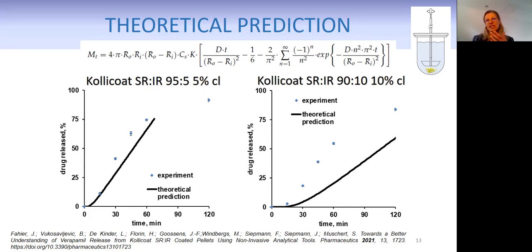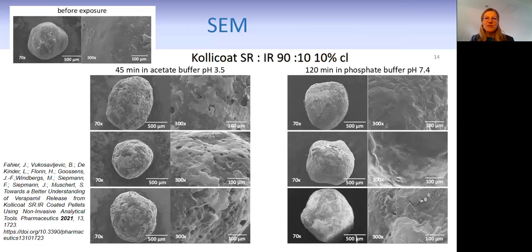So that leaves us with the theory of the cracking of the film coating, which can be observed by scanning electron microscopy. Here you can see an example for the Kollicoat SR:IR 90:10 coating. In acetate buffer, we actually have some holes and cracks appearing. Also, after exposure to phosphate buffer for 2 hours, you can see cracks appearing. However, scanning electron microscopy needs to be performed on dry pellets. So we needed to dry the pellets after exposing them to the dissolution medium by vacuum drying, and this can cause artifacts, meaning we could actually induce cracks in the film coating by drying them.